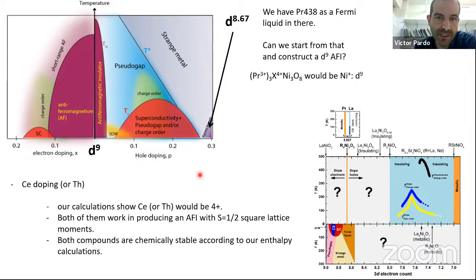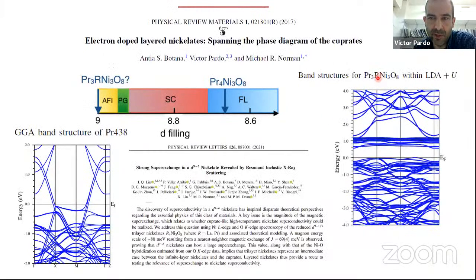So we did the calculations, and with this introducing here the cerium instead of praseodymium, what you end up having is the opening of a gap, and the system wants to be antiferromagnetic in the plane. So this point we know it from experiments, and this point we have calculated it. Whether what happens in between is like in the cuprates, we just don't know.